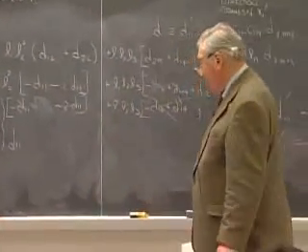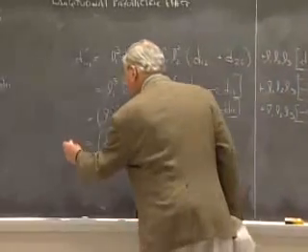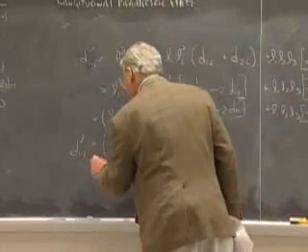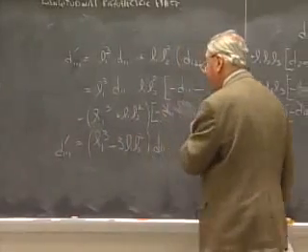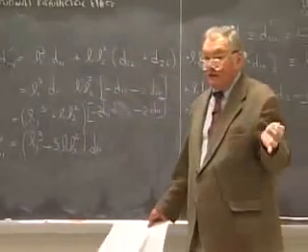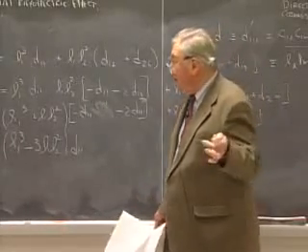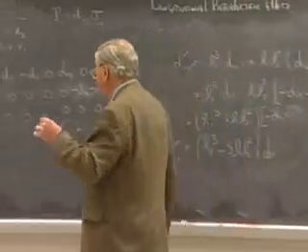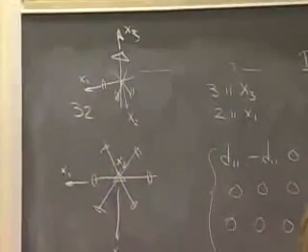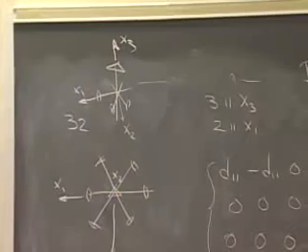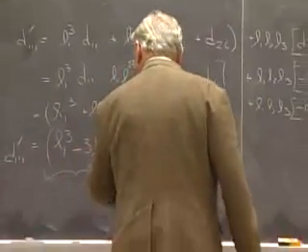Okay, so what we have ended up with is an expression for the longitudinal piezoelectric modulus as a function of orientation. The surprising thing is that L3 does not appear here at all. It doesn't depend on the angle between the normal to the plate and the threefold axis. Depends only on one modulus, and that is a remarkable thing.